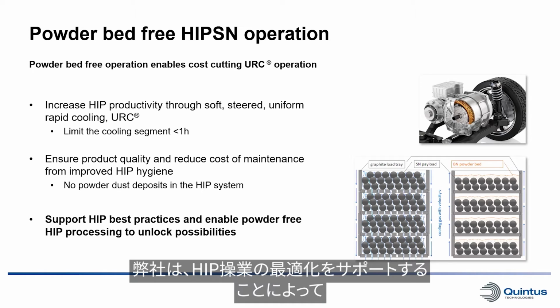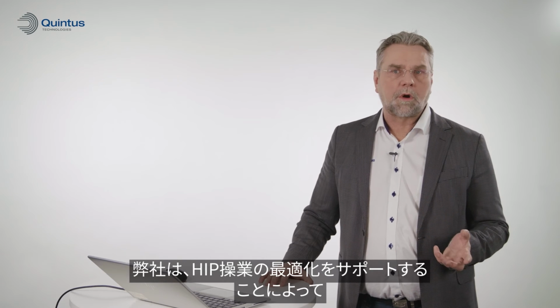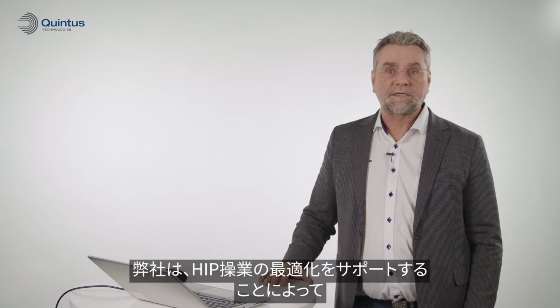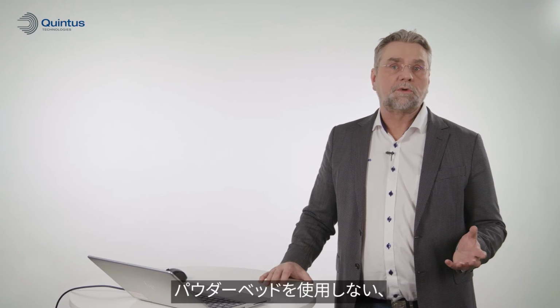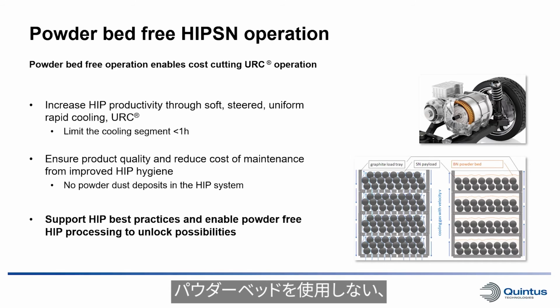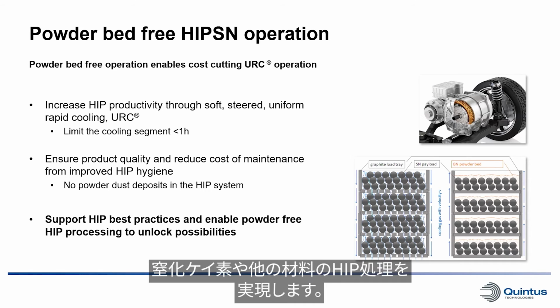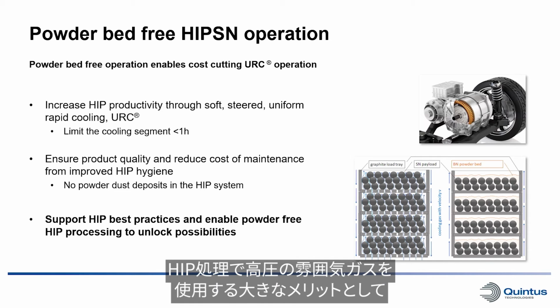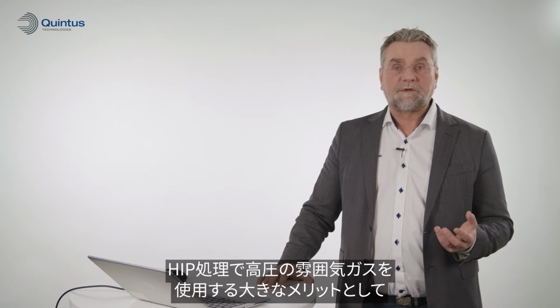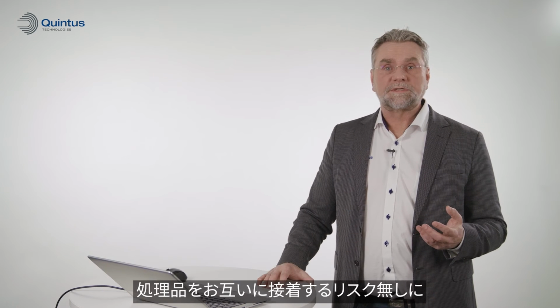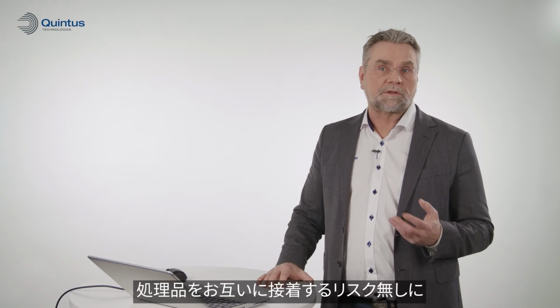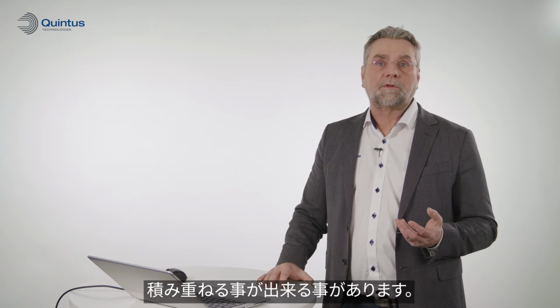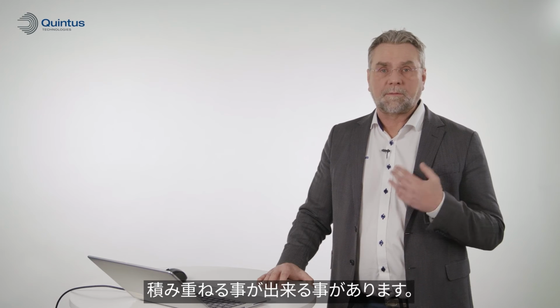So, we want to make sure that we support the best practice in HIPping, so we can enable the powder bed free HIPping of silicon nitride and also other materials. One big benefit of using high pressure atmosphere in the HIP is, of course, that we can stack components on top of each other without risking them bonding together.